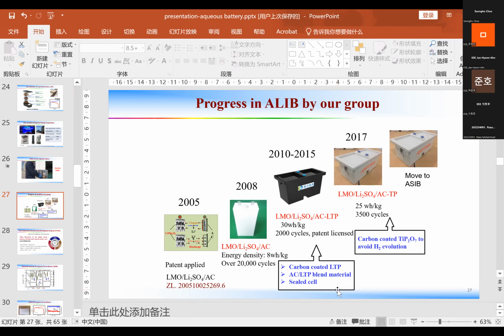At first, I introduced the advantages and disadvantages of these systems compared to lead acid batteries. The conventional lead acid battery normally has limited cycling, maybe 300 to 500 cycles, for example for electric bicycles. For those batteries, the specific energy is around 35 or 40 watt-hours per kilogram. So it's limited, and the cycling stability is low. So I think for aqueous lithium batteries, the possible application markets will be energy storage batteries for stationary power sources, not electric bicycles, because the specific energy is low.